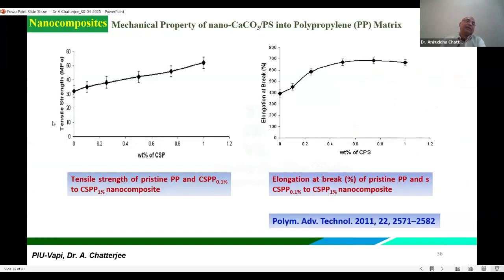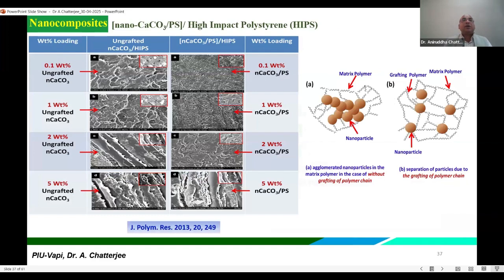Again, as we incorporated this core shell nanostructure in the polymeric matrix, tensile strength is continuously increasing from 0 to 5% of loading. And elongation at break is also continuously increasing. This is about calcium carbonate, the same core shell structure, in high impact polystyrene, here with 0.1 to 5% of loading.